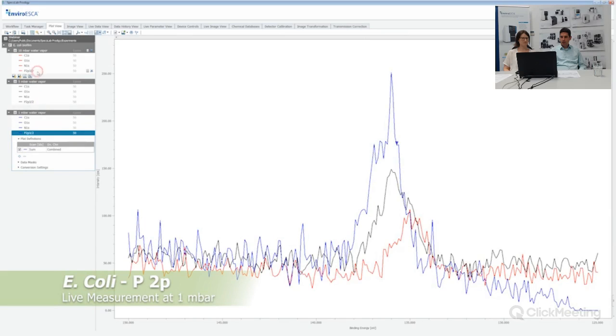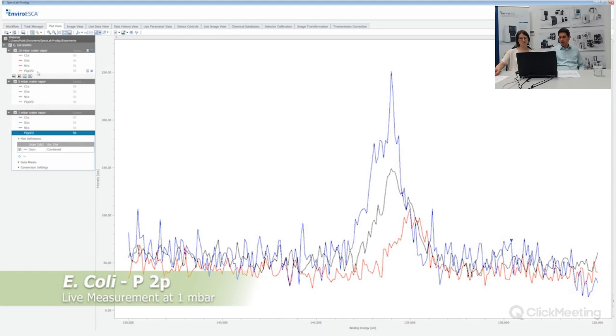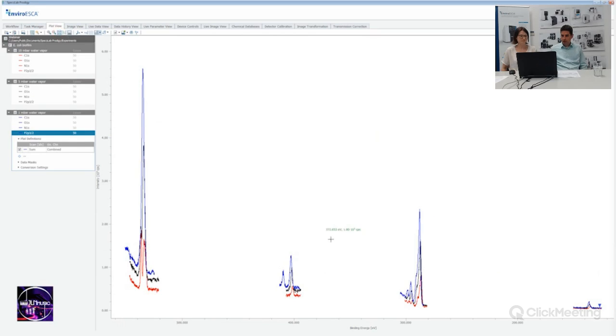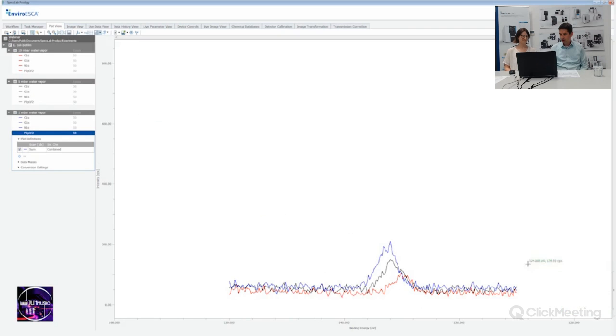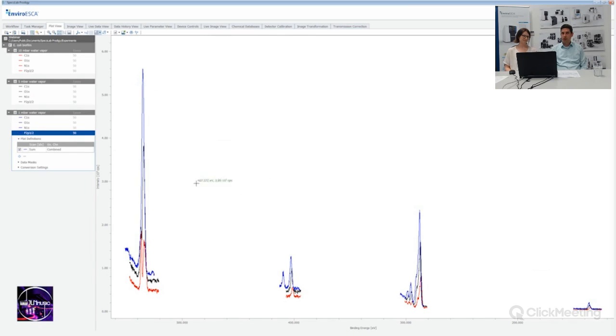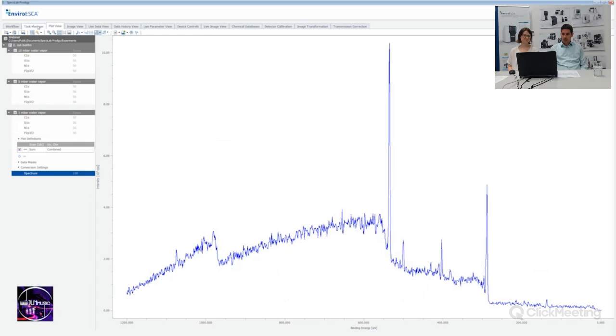Again, the last one is the phosphorus compared to the other ones. And also here you see the slight shift in binding energy, but you see the significant increase in intensity from 10 to 5 and 1 millibar. And with that, it's almost done. In the end, you will see that there's also a survey spectrum showing all the different elements. And with that, we hope we could demonstrate to you how near ambient pressure XPS measurements of bacterial films can be realized in an easy way and also in a pretty fast way, if you think that we measured 4 different elements at 3 different pressures.